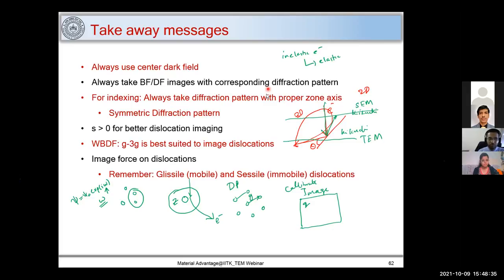So TEMs which have goniometers of plus 30, minus 30, those kinds of TEMs are useful for dislocation imaging. If you go for HRTEM and the like, they don't have proper tilt, so you can't tilt your sample much. Those have tilt of less than 10 degrees also. So if you are not able to do that, I think there is less chance you can image it.